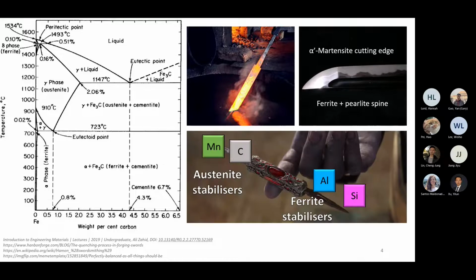All right, so we know in steels you also have more alloying elements other than carbon. You've got manganese, nickel, chrome, aluminium, silicon. And these elements you can really split into the austenite stabilizers. So austenite stabilizers make this window here bigger, so it makes it larger, and even actually stabilize the austenite phase down to room temperature. So your ferrite stabilizers, they do the opposite. They make the austenite window smaller.